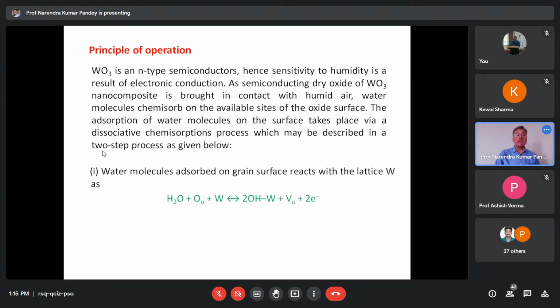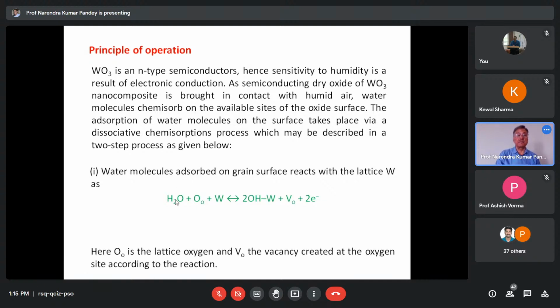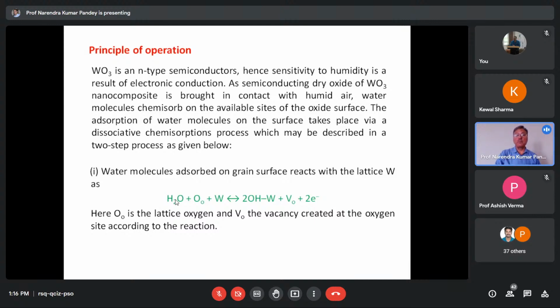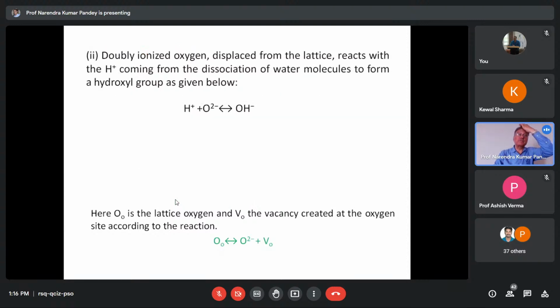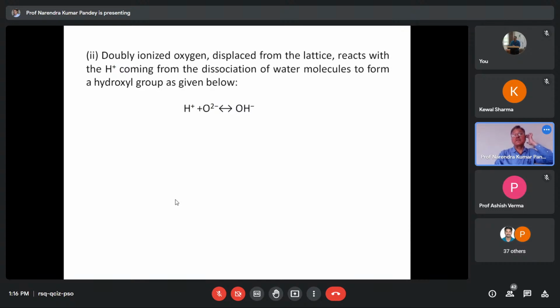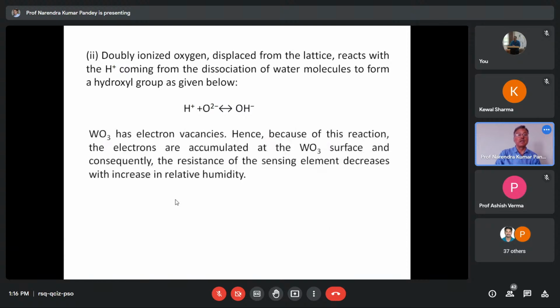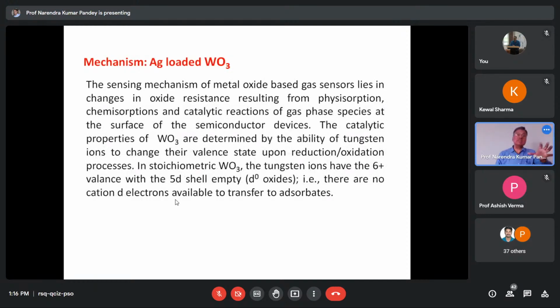What are they? This is the first reaction. Molecules get adsorbed on the surface and react with lattice W, as in this one. This is one reaction. Then Oo is lattice oxygen and Vo is the vacancy created, right? And then we have this oxygen vacancy. The ionized oxygen displaced from the lattice reacts with the hydronium ion coming from the dissociation of water molecules to form a hydroxyl group. WO3 has electron vacancies. Hence, because of this reaction, the electrons are accumulated at the WO3 surface and consequently, the resistance of the sensing element decreases with increase in relative humidity. That is a simple picture.